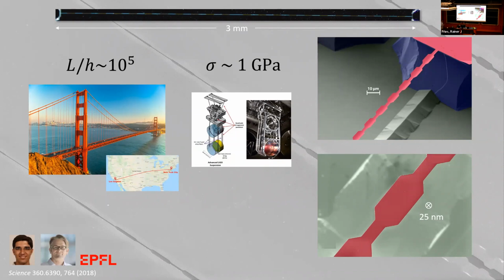This is near the yield strength actually of most glassy materials. It's near the yield strength of silicon nitride. To get a sense of scale for that, if you took an optical fiber, 100 micron diameter optical fiber, and suspended a bowling ball from it, you would get this type of stress. And this situation actually naturally arises in, for example, suspension springs for gravitational wave test masses.